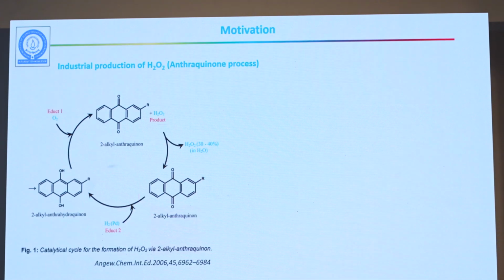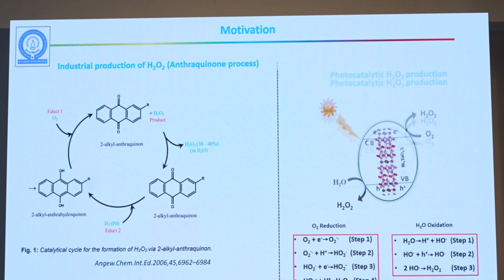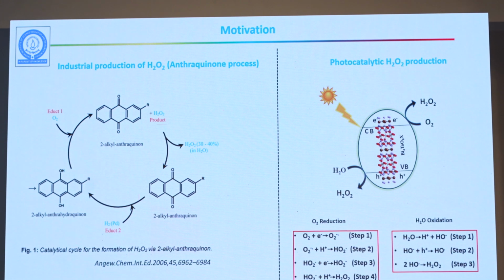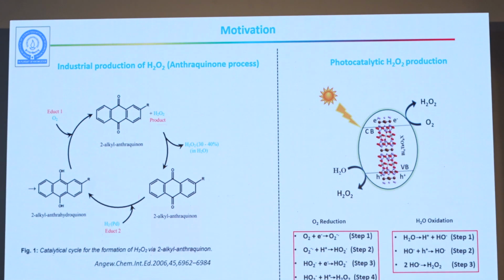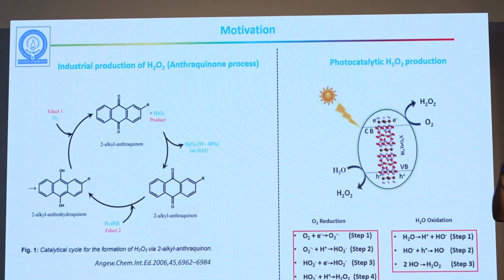So the idea in this case, so this is the conventional method. Again, I am not going into the details, except the fact that we have to use oxygen, we have to use palladium, and we have to use high pressure hydrogen. It is not only expensive, it is also dangerous, and needs high temperatures. All right, the idea is that if you can use a photocatalyst and you can get oxygen molecules from air, somehow, if you can put 2 protons, it becomes H2O2. It's a very simple reaction.